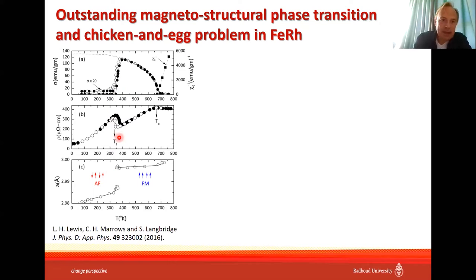If you measure the conductivity, you see that here the conductivity changes suddenly at the temperature phase transition. People also observed that the lattice of iron rhodium changes at the temperature phase transition. And also here you can see a confirmation of the fact that magnetization increases upon temperature increase, if you're sitting here, upon temperature increase from 300 to 400 Kelvin.